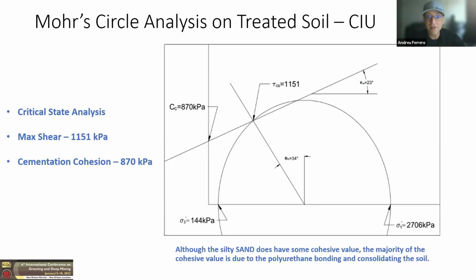We conducted a Mohr circle analysis on the treated soil and found a value of about 870 kPa cohesion. That silty part of the sand does add a little bit of cohesion to the sand itself, but we were postulating that the majority of the cohesion is from the polyurethane treatment and what we're calling a cementation cohesion value.